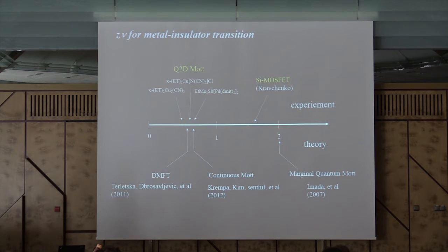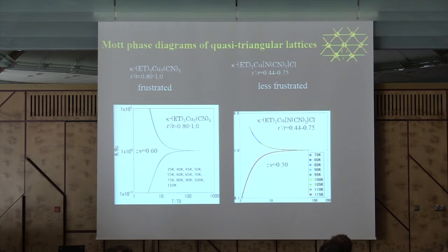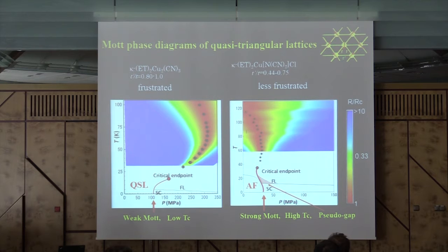But I can say that there is a possibility that this difference is meaningful and makes sense, because this Mott transition is not followed by symmetry breaking. In usual quantum phase transitions there is an order parameter. For example, in heavy fermion systems, a magnetic order is the order parameter, and the order parameter is fluctuating quantum mechanically. But in this case, there is no order parameter. So this quantum critical behavior is very unconventional and non-trivial, I think. So I think much more should be done from experimental and theoretical points of view. Okay, this is a kind of conclusion of the first part of my talk.